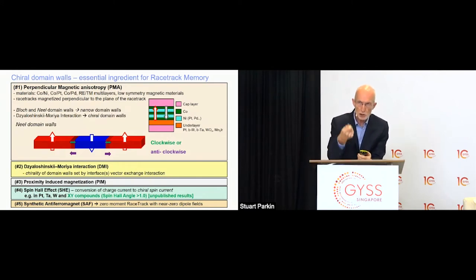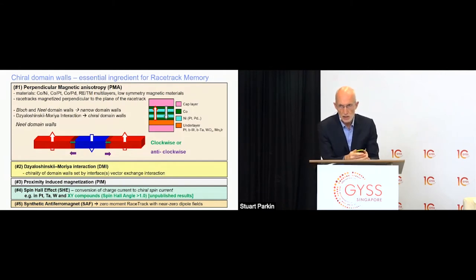But it's a very special interaction in that it's a vector exchange, and that perpendicular orientation of the moments actually also has a chirality. So you can see in this cartoon, when we switch from a red region in the racetrack magnetized up to a blue region pointing down, the magnetization will rotate in a plane perpendicular to the domain wall, such that, as shown here in the cartoon by the green arrow, the magnetization in that domain wall will point to the right. But when in the same material, the magnetization rotates from a blue to a red direction, then the green arrow in the middle of the domain will point to the left. And the basic Dzyaloshinskii-Moriya interfacial interaction causes the domain walls in this perpendicularly magnetized cobalt nickel layer to both be what is called a Néel domain wall and to have a chirality.